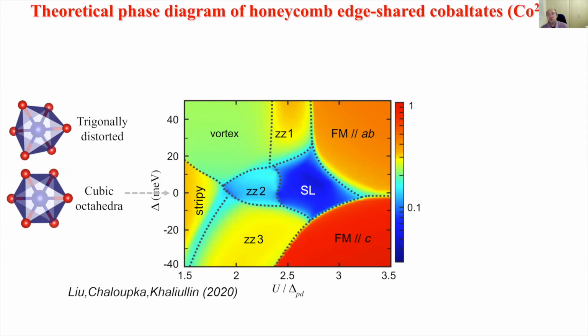Because we know that in our sample we have these 6 domains. Of course, 3 are related by 120 degrees, and then each one can have spin reversed. Now the reversed pairs have identical dispersions, but the other ones have slightly different dispersions. So there could potentially be some detailed information about what happens close to the touching points, which direction they move, and so on. If we're able to use strain on an inelastic neutron scattering sample in a controlled way, and select a single domain, that could potentially give some additional information about the mechanism of the ground state selection and so on. That could distinguish between scenarios.